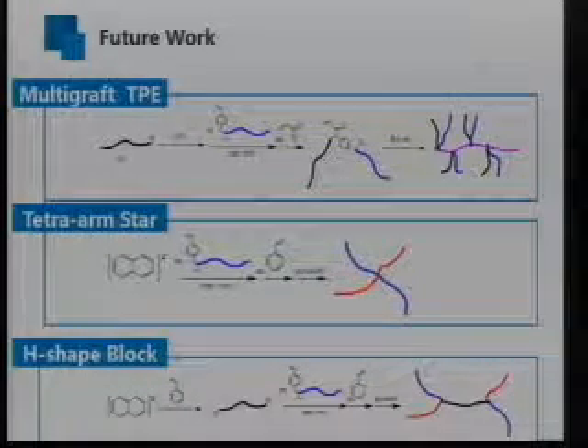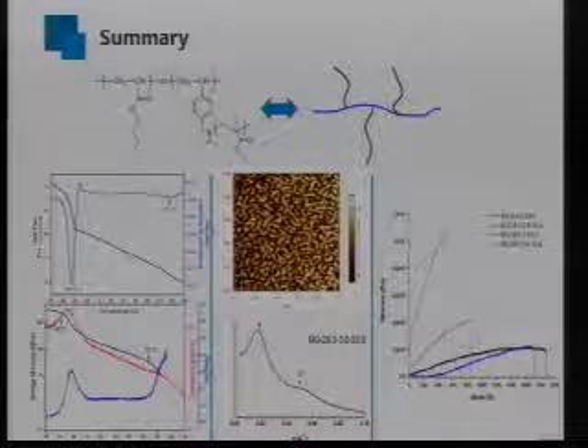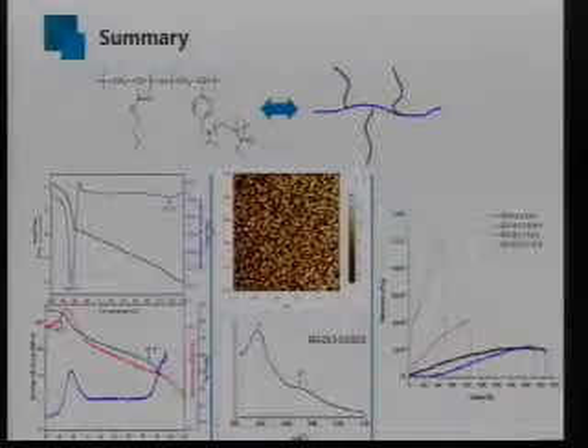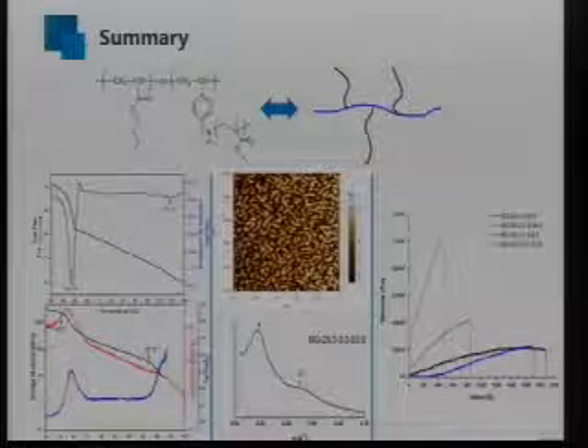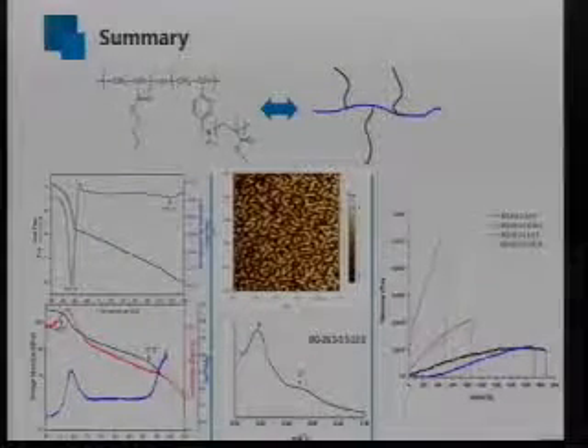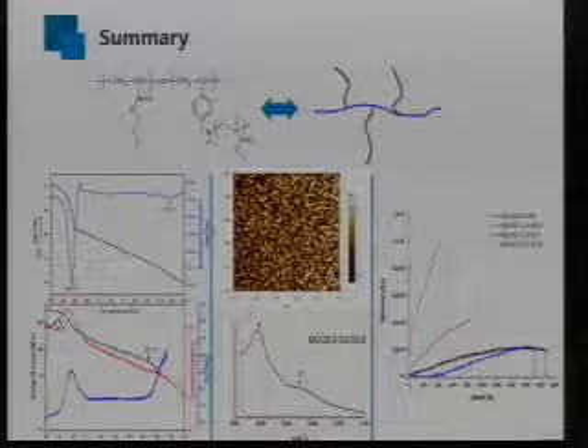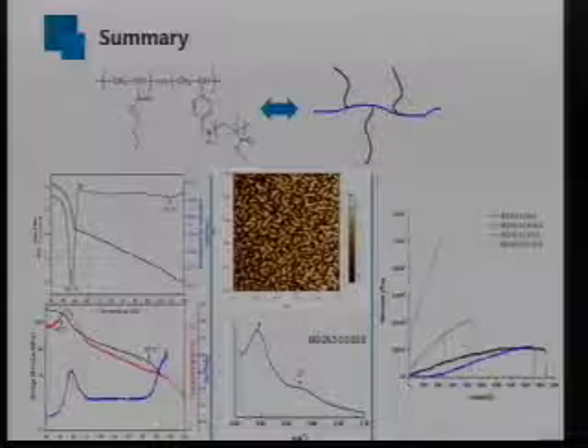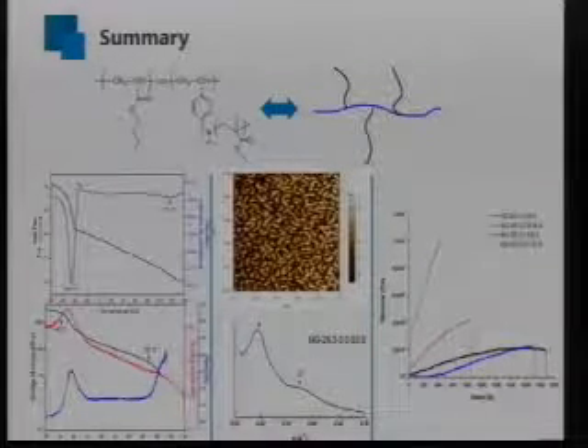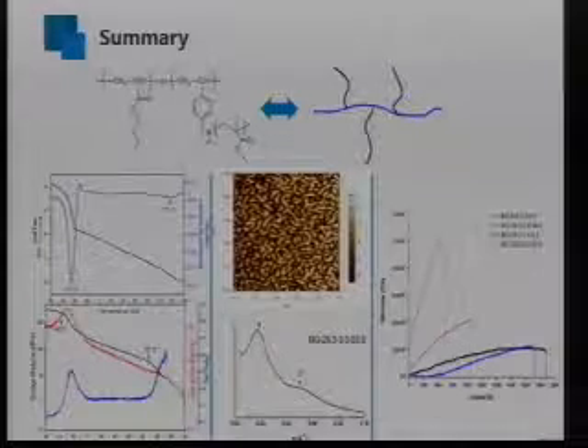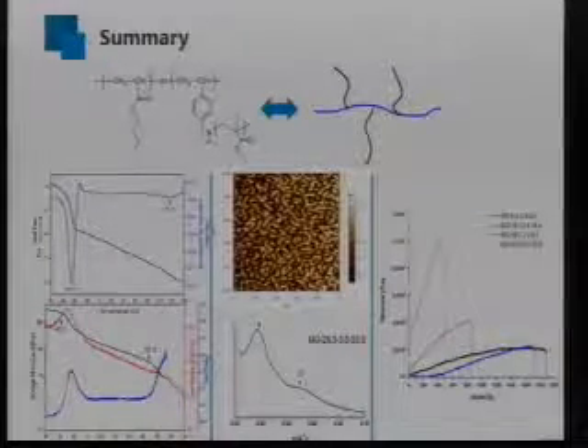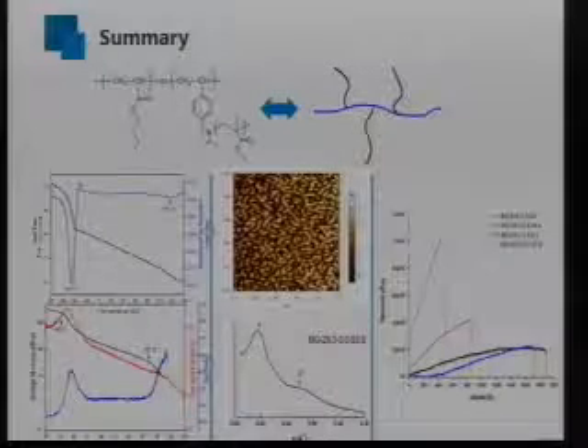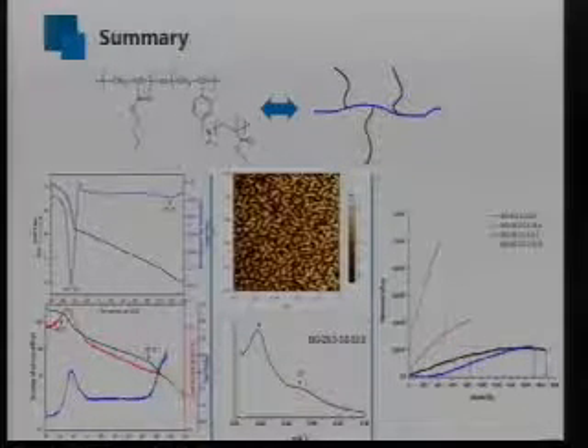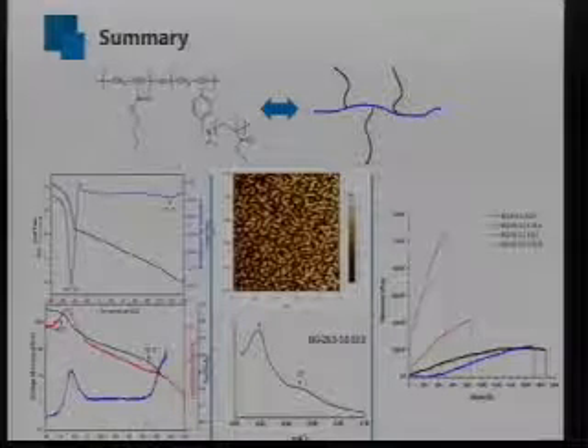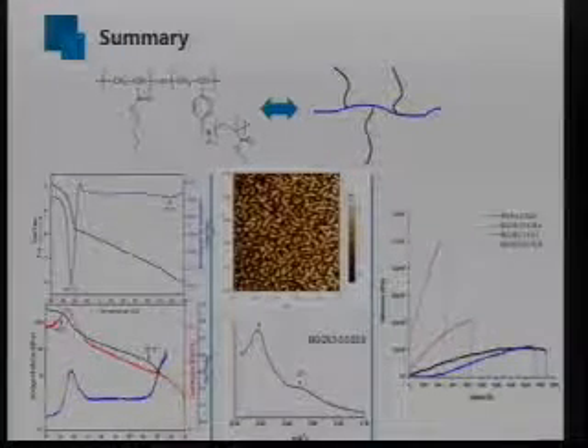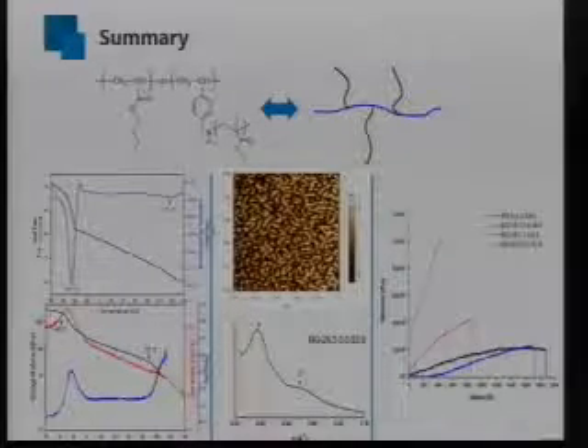So as a summary of our work, first, we successfully synthesized the graft polymer of polybutyl acrylate, graft polybutyl methacrylate, with a very simple operation, which showed very clear two-step transitions from both DSC and DMA. And both AFM and SAXS showed a very distinct microphase separation behavior. This material can give the elongation longer than 1700% with very good strain recovery, for which we can conclude the successful polymerization of all-acrylate multigraft copolymer superelastomer.